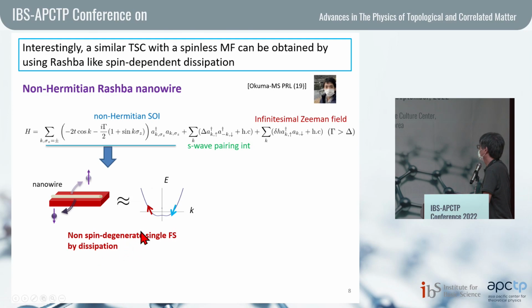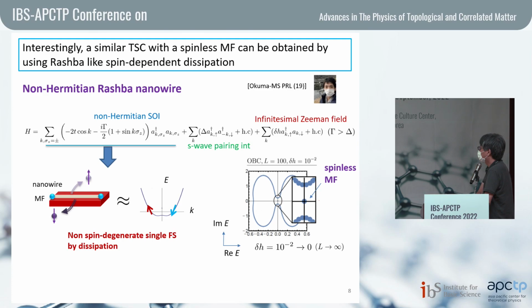So according to our simple Fermi surface criterion, we can expect a spinless Majorana zero mode. And actually, we can obtain a spinless Majorana fermion in this case. Here I show the quasiparticle spectra in the superconducting state. Since we are considering the non-Hermitian term here, the spectrum can be complex. However, in addition to the bulk spectrum, we also have a zero energy mode, and this corresponds to the spinless Majorana fermion. In this picture, we consider finite size systems, so a very tiny magnetic field is necessary to realize this picture. This magnetic field can be zero in the thermodynamic limit. So anyway, because of this structure, we can obtain a spinless Majorana fermion.